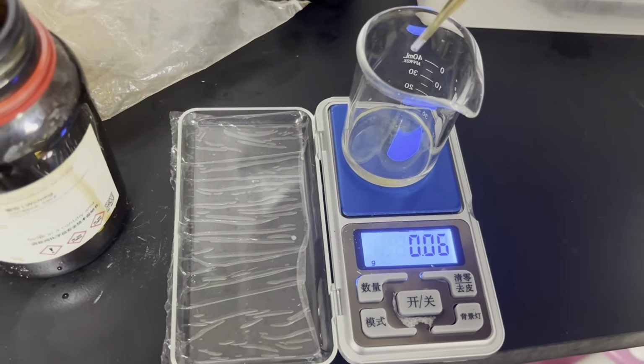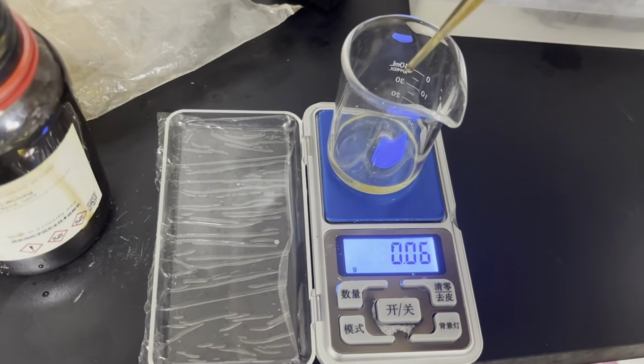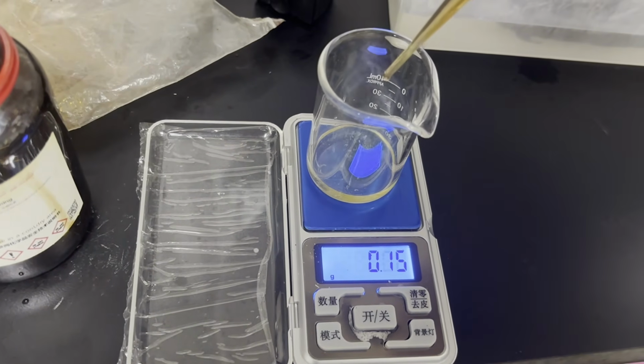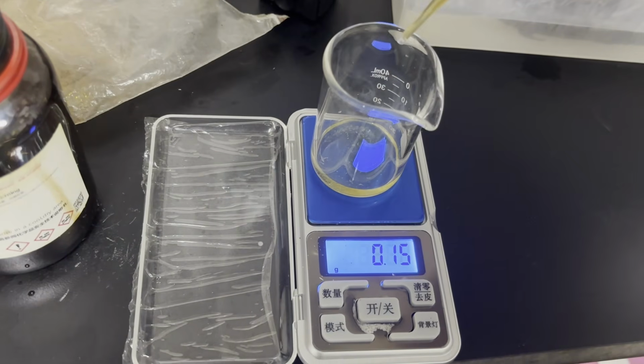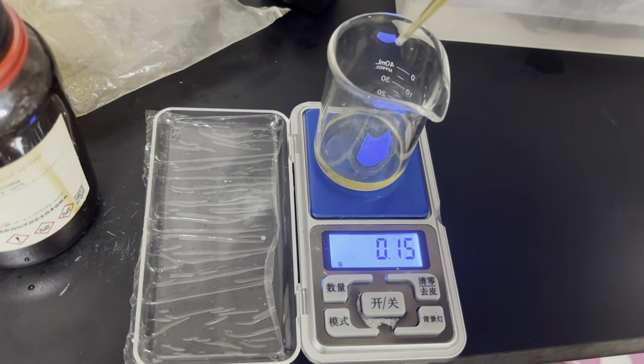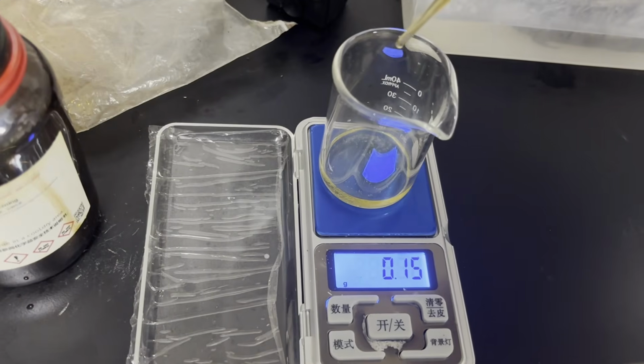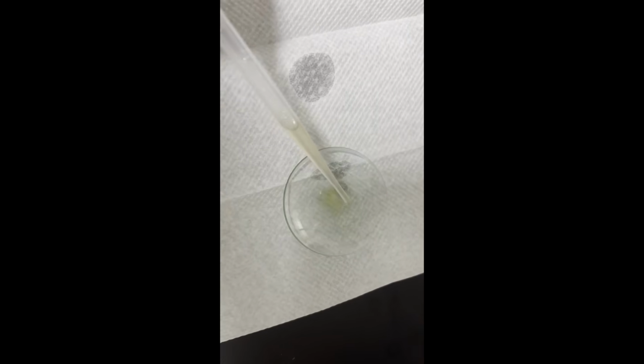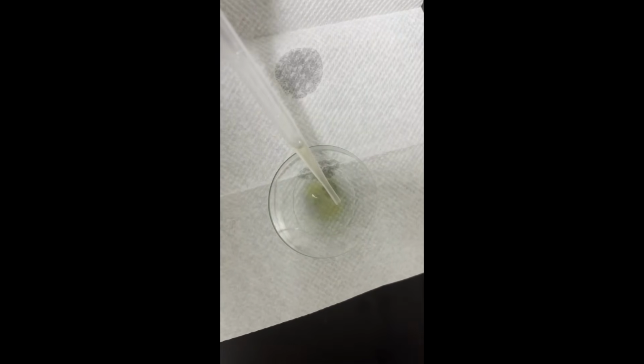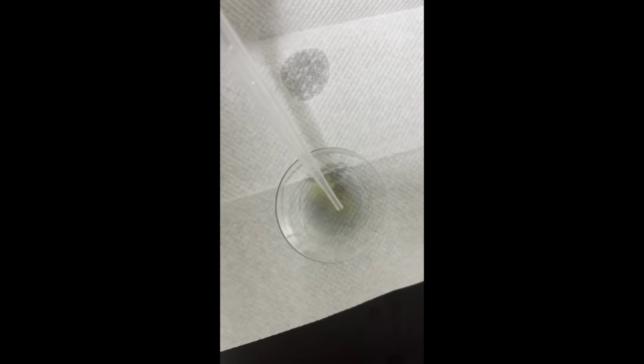To 5 ml of 20% hydrochloric acid, I added 0.2 grams of aniline. The aniline produced fumes in contact with hydrogen chloride released from the acid and dissolved quickly to produce a clear, light yellow solution. I then added around 2 milliliters of the solution to a sample of cell electrolyte. It is clearly seen that the mixture turned to a distinct blue, which then darkened to almost black. This is a positive test for medium amounts of chlorate, as aniline is oxidized by chlorate in acidic conditions to produce polymers, perhaps aniline black that was showcased in one of previous videos.